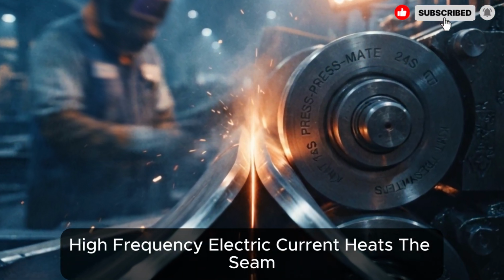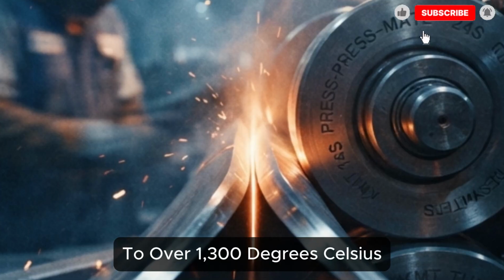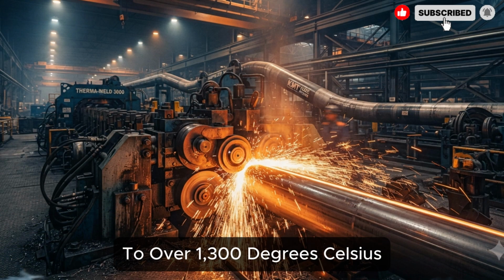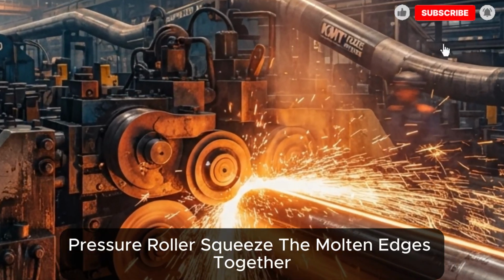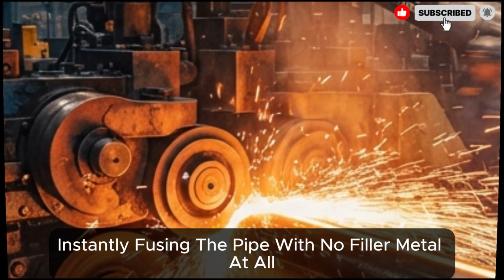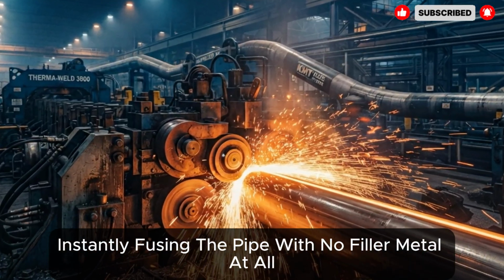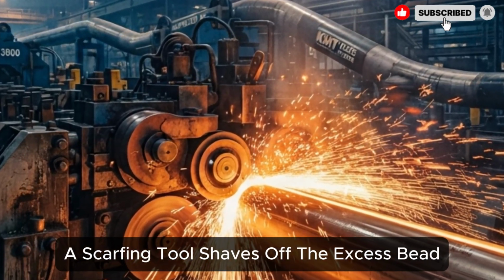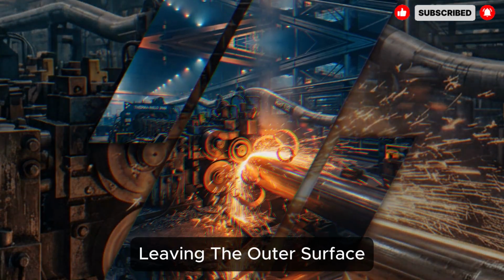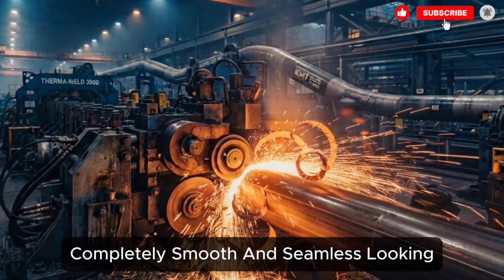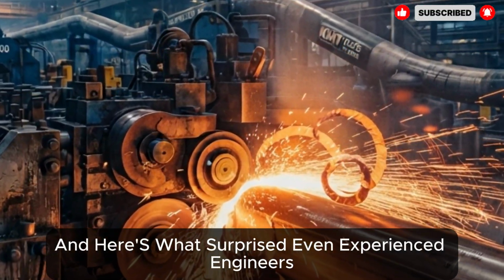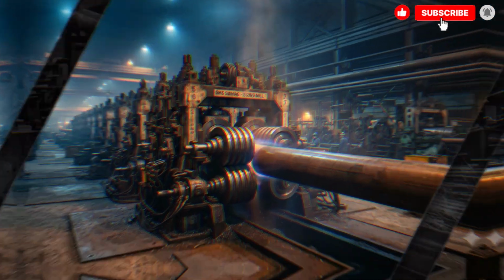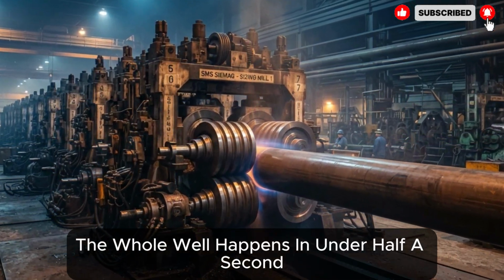High-frequency electric current heats the seam to over 1,300 degrees Celsius in seconds. Pressure rollers squeeze the molten edges together instantly, fusing the pipe with no filler metal at all. A scarfing tool shaves off the excess bead, leaving the outer surface completely smooth and seamless looking. And here's what surprised even experienced engineers. The whole weld happens in under half a second.